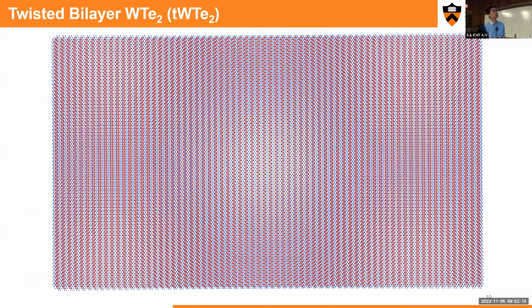Sorry, the animation is not so good. If you look here, the Moiré unit cell is still rectangular, but it also shows a stripe feature like this. If I remove all the tellurium atoms, you are going to see a 1D stripe in this way. Experimentally, and also theoretically, you can calculate the distance between the wires, and you can engineer your twist angle to reach whichever number you want. The long width and the short width ratio is around 1 to 2.